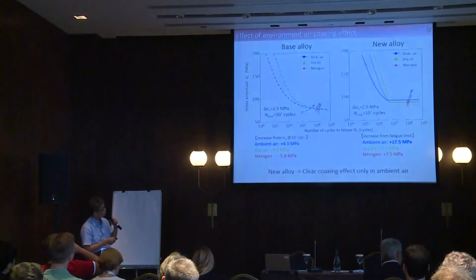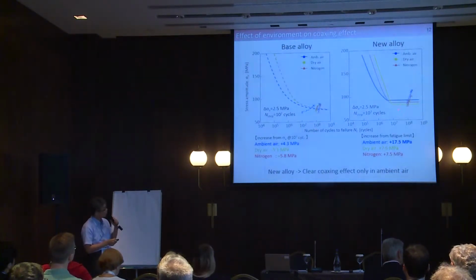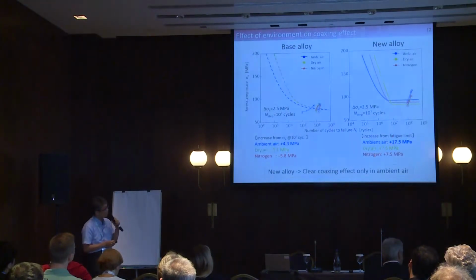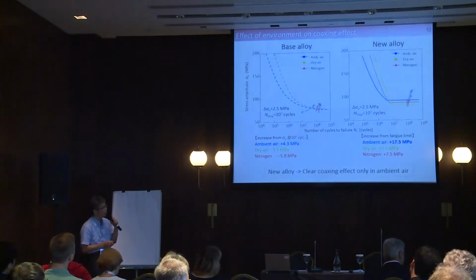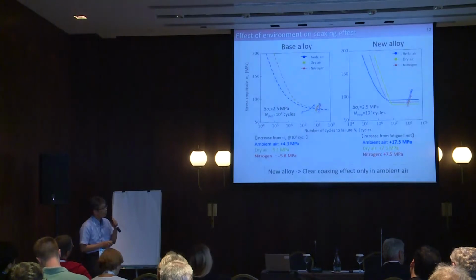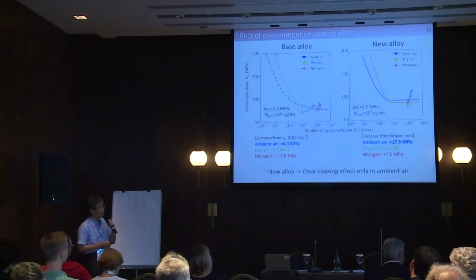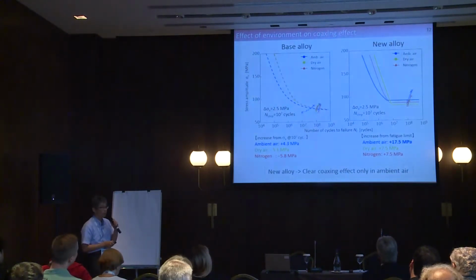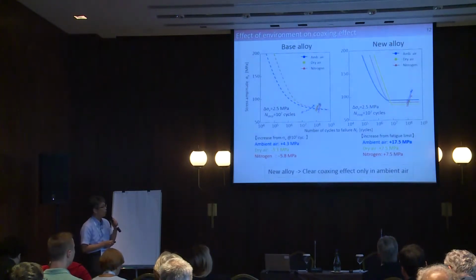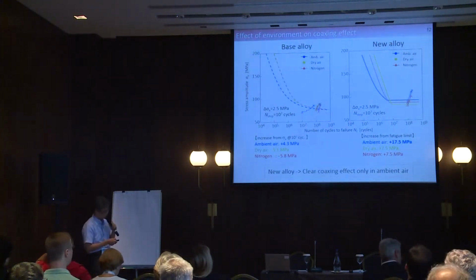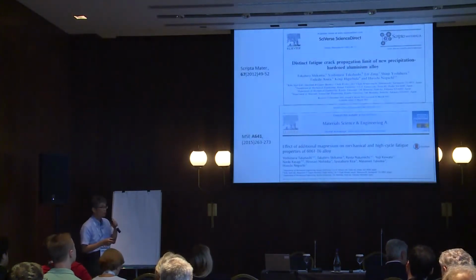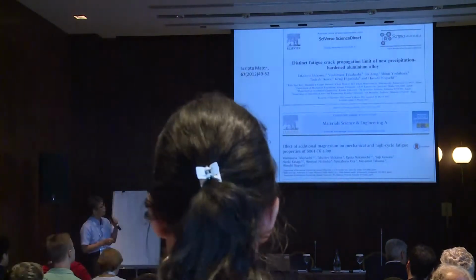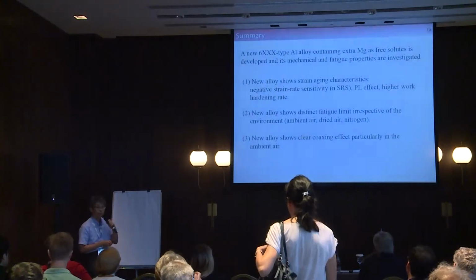And finally, the stress step-up test. The new alloy shows the coaxing effect, but the base alloy doesn't. And what's interesting here is that in the ambient air, the coaxing effect is very pronounced, about 18 megapascal increase of strength. But in dried air or in nitrogen, the effect is a little bit smaller. At this moment, we don't know why such an environmental difference arises. Maybe the contribution of added extra magnesium to the strengthening may be different, but it's open for discussion later. And these results, except for the final environmental effects, are contained in these papers. Thank you very much for your kind attention.